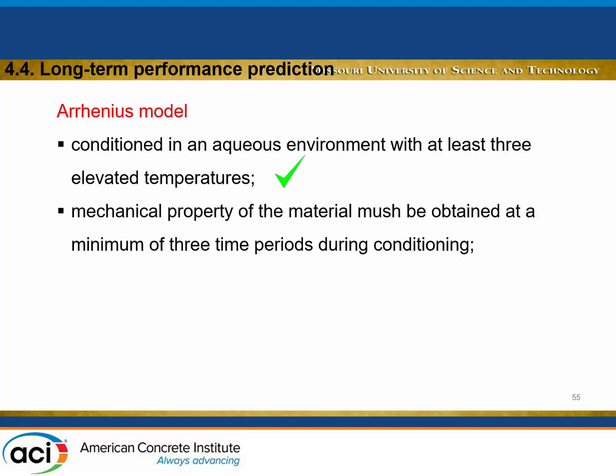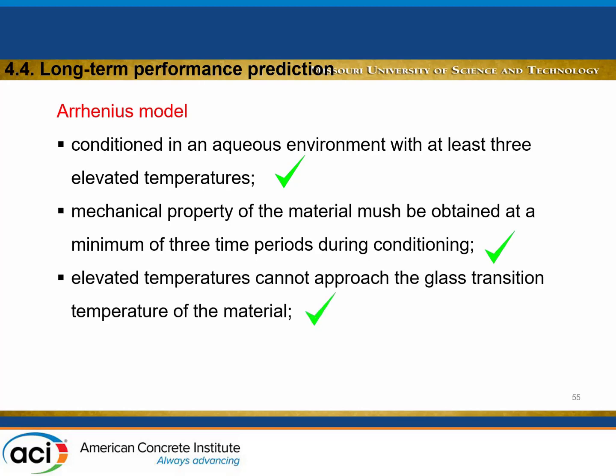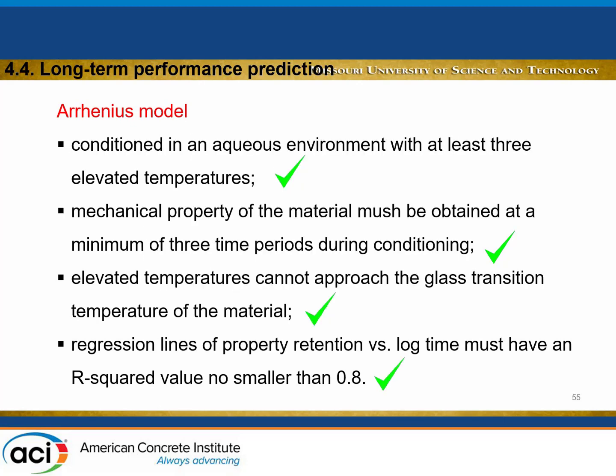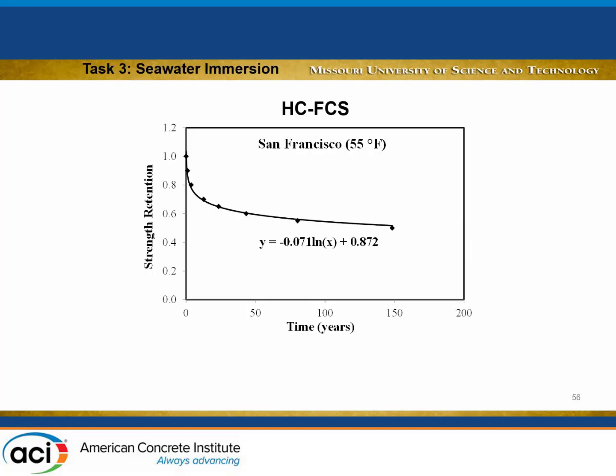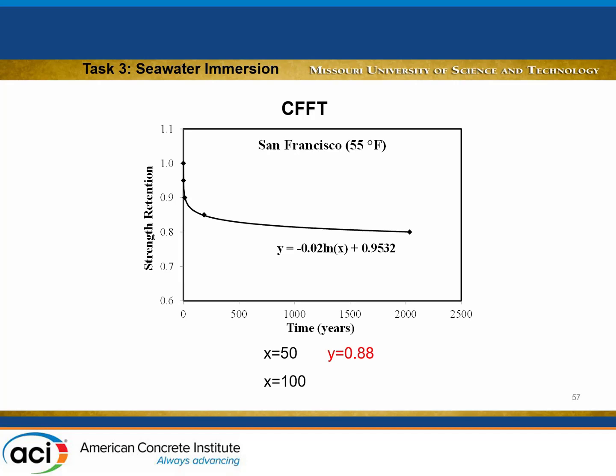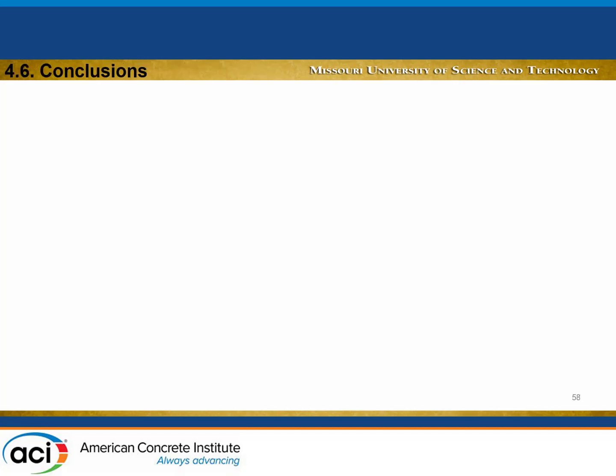Then we used Arrhenius model to see how this would be reflected in the long-term behavior. For example, we talk about a few cities here. We take San Francisco, and we assume different service lives: 50 years, 100 years, 150 years. At 150 years, you lose about 50% of the capacity of your column, at 55 degrees and using this exposure. Then we ran the same analysis for concrete filled fiber tubes, for different cities across the US.